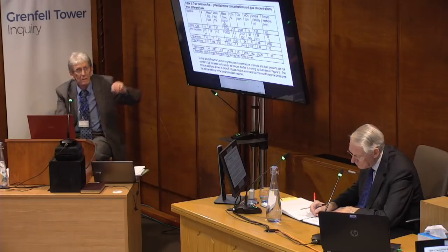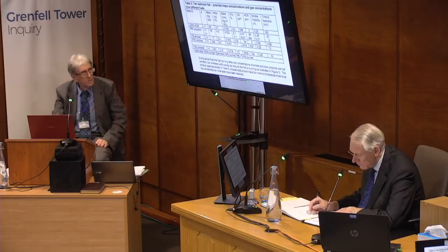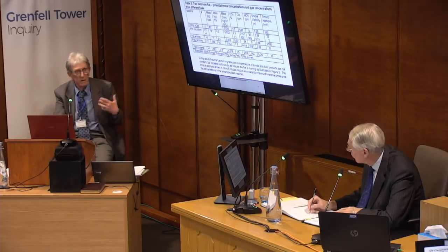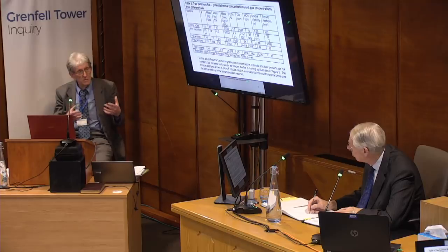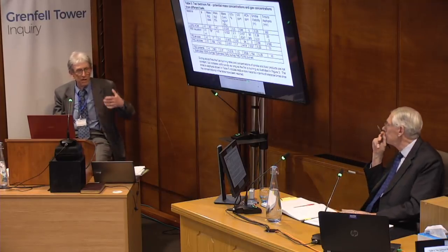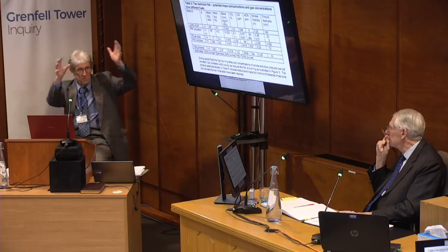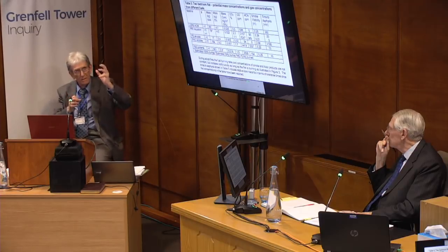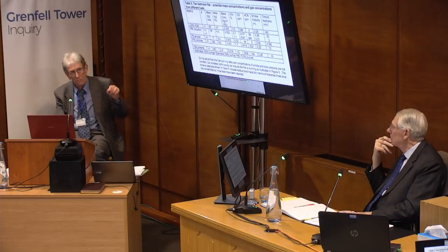Yes. I mentioned it as a phenomenon, but I've only factored it into my calculations here insofar as it affects the PVC itself. So PVC, when you burn it, even with a flame, which is quite hard to do, produces, as I've said, a very high yield of carbon monoxide. That is because the chlorine content is roughly 50% by mass, and it is all released as hydrogen chloride. This is a free radical scavenger, which means that it limits oxidation reactions in the flame zone above it. So instead of the carbon gases being burnt to completion, you get a high yield of partial combustion, which is the carbon monoxide. That's why we get such a high yield of CO from PVC itself.